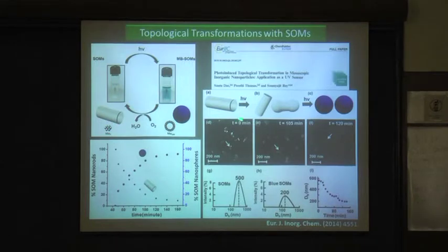When we shine light on it, we generate these circular ring-like structures, which provide us with a C5 unit and thereby induce a surface defect on the linear rods, and we get these spherocylindrical species. And then with longer irradiation time, we start getting these spherical species, which become blue because of the presence of Mo5, Mo6 intervalence charge transfer transitions.